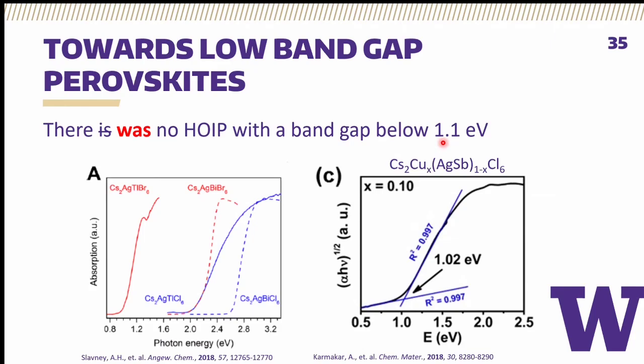absorption in your devices. So this absorption could be due to the bulk crystal, or could be, as in the case of bismuth doped methyl ammonium lead bromide, just direct absorption to a defect band that doesn't contribute electrically to whatever device you want to make with this material. And so to avoid that risk, we went with the cesium, silver, thallium bromide.